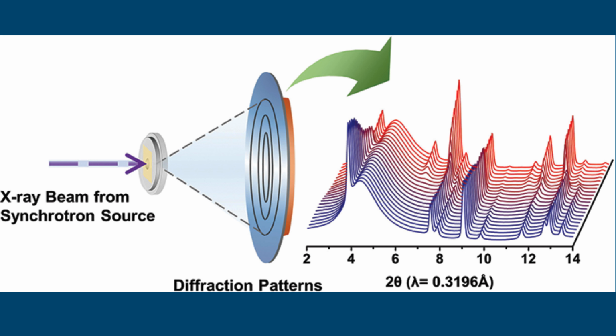Synchrotron-based XRD further enhances analytical sensitivity by utilizing highly intense and tunable X-ray beams generated from particle accelerators. These systems enable in-situ and operando measurements under extreme conditions such as high temperature, high pressure, or electrochemical cycling.